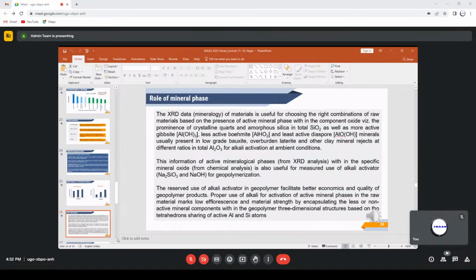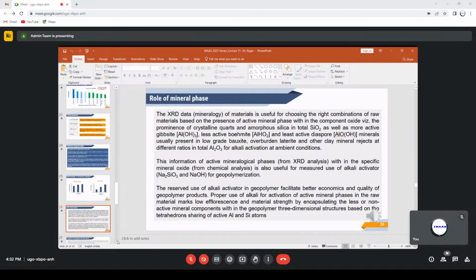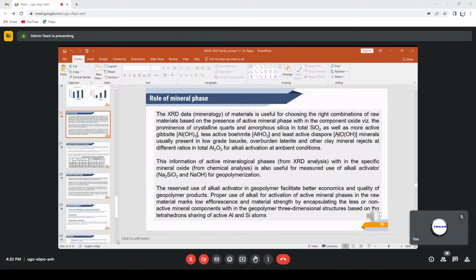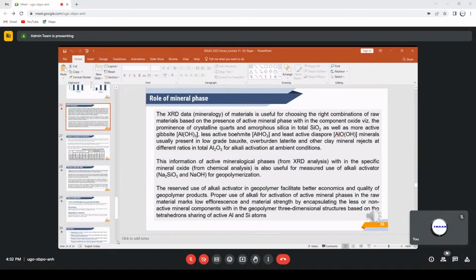It was observed that the XRD data or mineralogy of the material is useful for choosing the right combination of raw materials based on the presence of active mineral phases within the component oxide. For example, the prominence of crystalline quartz and amorphous silica in total silica, as well as more active gibbsite, less active boehmite, and least active diaspore in minerals usually present in low-grade bauxite, overburden laterite, and other clay mineral rejects at different ratios in total alumina for alkali activation at ambient condition.